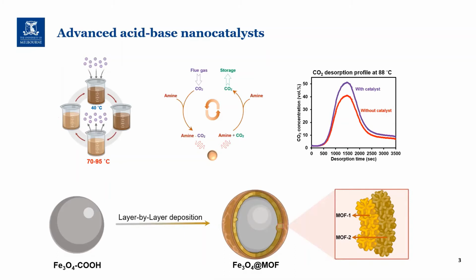In this technique, catalysts can enhance the desorption efficiency, promote carbon dioxide desorption rate, and decrease total energy consumption during the solvent regeneration process. Apart from these benefits, catalyst addition also enables the solvent to achieve a regeneration temperature below 100 degrees Celsius rather than 140 degrees Celsius without using catalysts, which can be regarded as the main benefit of catalytic solvent regeneration.